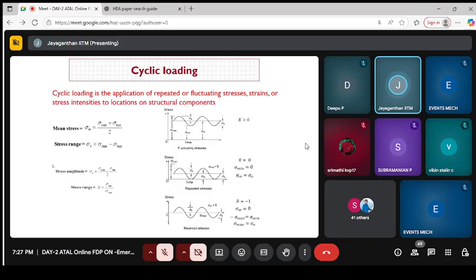The loading pattern could be periodic. You can even have a loading pattern with variable amplitude also. So we are trying to highlight the role of mean stress, stress range, stress amplitude, and stress ratio, and whether the loading pattern is fluctuating stress, repeated stress, or reverse stress. When I say reverse stress, what do the plus sign and minus sign indicate? You will have tension, or tension-compression, or compression. The loading being dynamic, when the load is acting on the sample, is it tension or tension-compression? You should know the loading pattern. That's where we characterize in terms of fluctuating stress, repeated stress, reverse stress, and so on, when you do the fatigue testing of the sample.